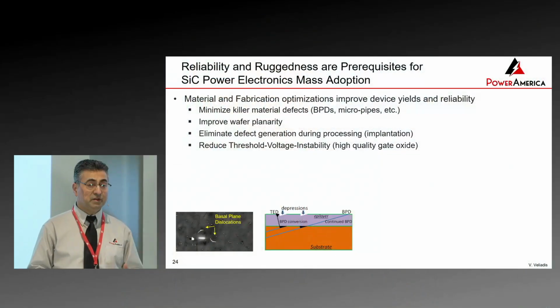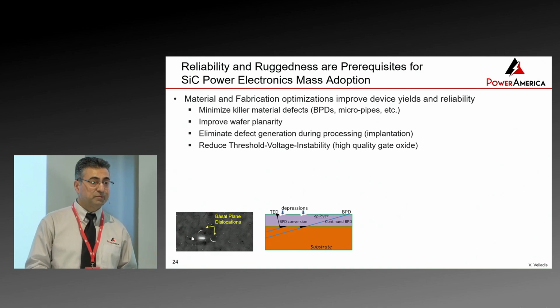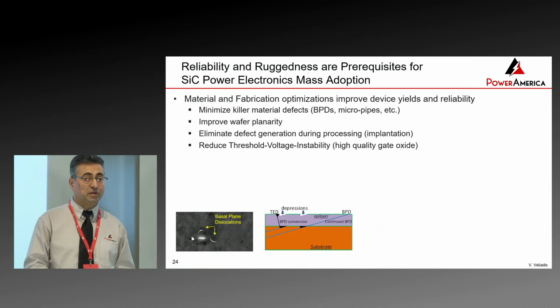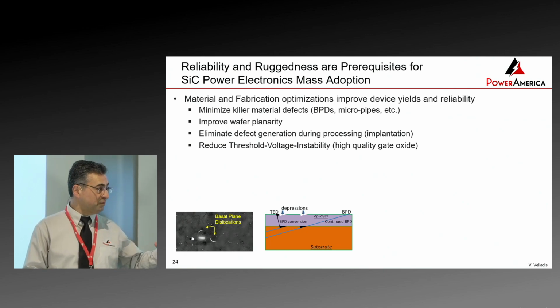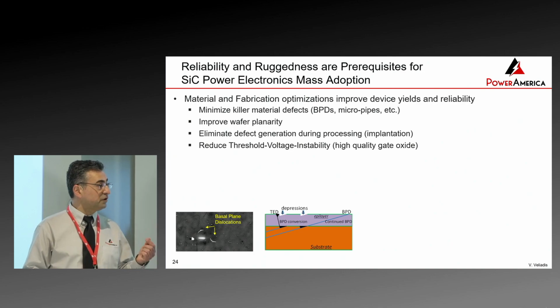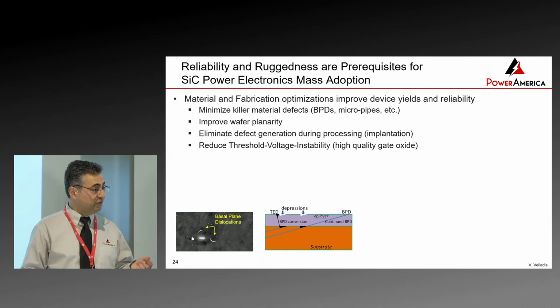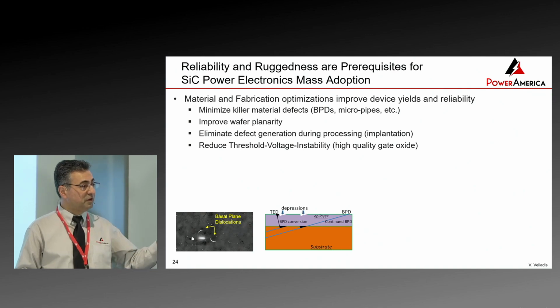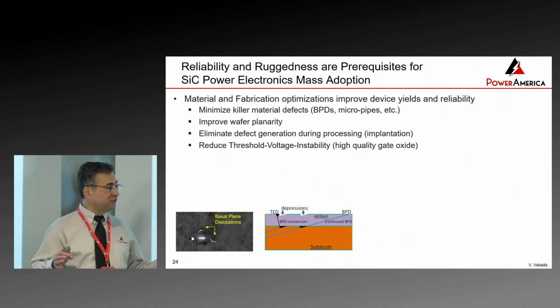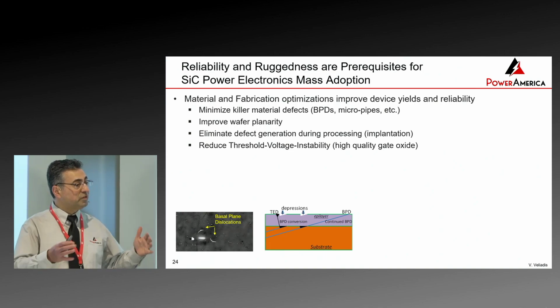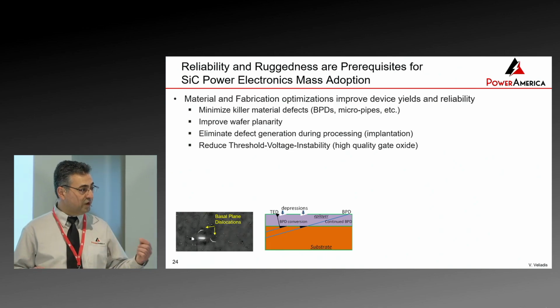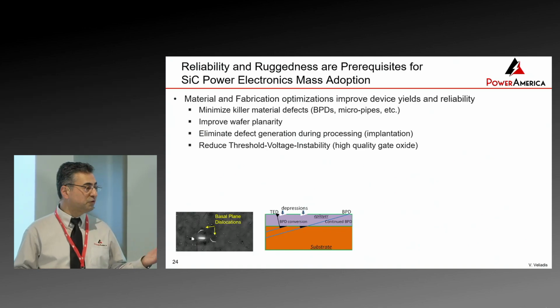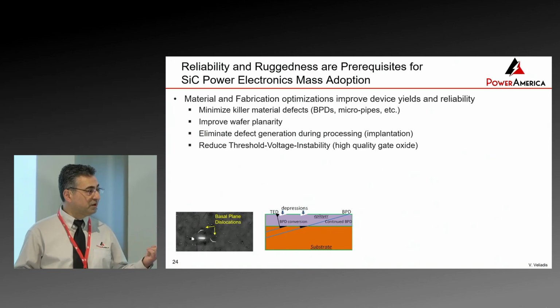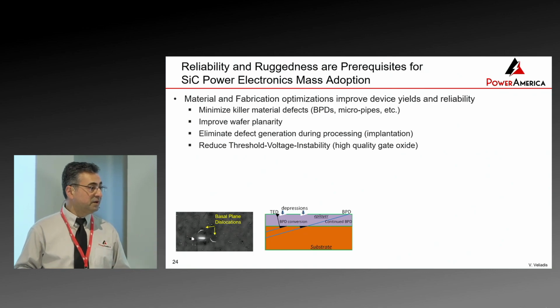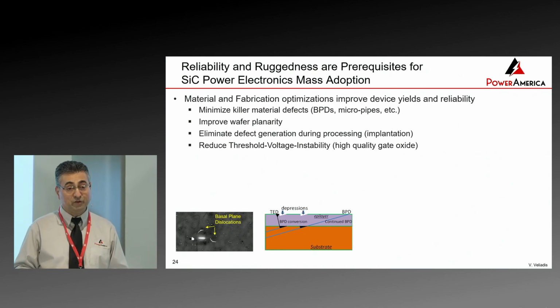Okay, so some of the last remaining items, with respect to the material, minimize killer defects. BPDs are the big one. You have to improve the wafer planarity, eliminate defect generation during processing. When you process silicon carbide devices, you can generate defects, and I've seen that. It's at the implantation levels. Some people that I was funding at XFAB, no defects were generated. With other processes, defects were generated. So there are ways to do it to not generate defects. And of course, because of the gate oxide, the trapping, you have threshold voltage instability, and that's one reliability issue that needs to be resolved.